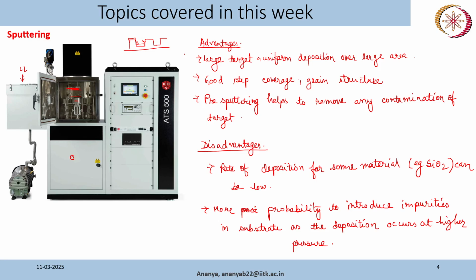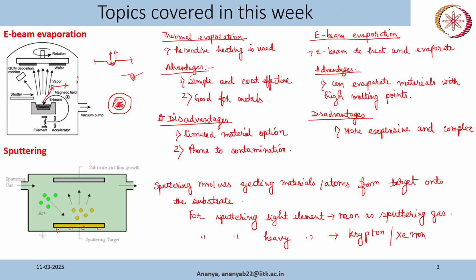Okay. And one thing you should also remember is that in case of evaporation, you are heating the material, whether it is thermal evaporation or e-beam evaporation. So even though there is a distance between your source and wafer, there will be some heat that reaches your wafer. So this is a practical problem that I'm telling you. Say, if you are doing your deposition at a very high temperature, that is usually necessary in case of thermal and e-beam evaporation.